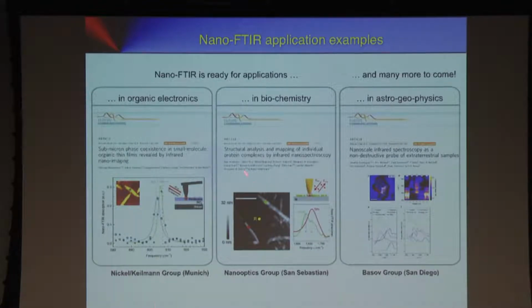This was our own work. Here I want to show you a work by Fritz Keilmann, and they showed submicron phase coexistence in pentacene molecules. They see that the structural ordering of these pentacene molecules leads to spectral shifts, and they could identify domains in these pentacene films where the ordering of the pentacene molecules is different. And that's a rather exotic application. This is from Dmitry Basov's group. That was done on stardust and meteorites, and here they look at phonons in meteorites, in minerals, to identify the chemical composition. So a vast variety of possibilities. One can look at nearly everything that one could look at with a standard infrared microscope.